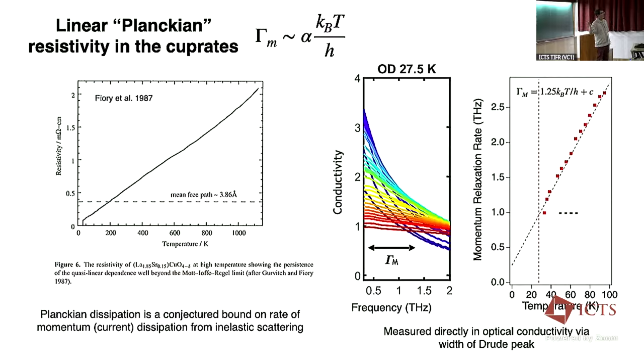So it's not nonlinear conductivity, it's linear conductivity. And this is near slightly overdoped lanthanum strontium copper oxide, and this is what we might call the Drude conductivity peak. It's the conductivity as a function of frequency, the real part. As you get down to lower temperatures, this peak gets sharper and sharper. And we plot here the width of this peak as a function of temperature. And it has this notable linear in temperature behavior, over a limited temperature range, but corresponds very closely to this linear in temperature range there.